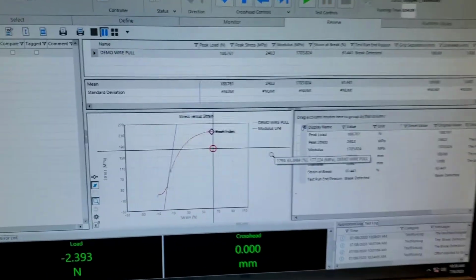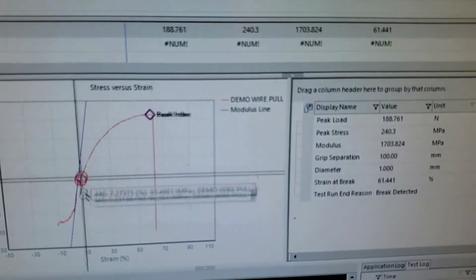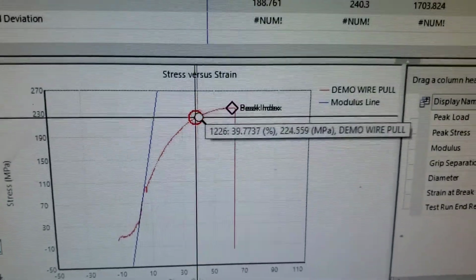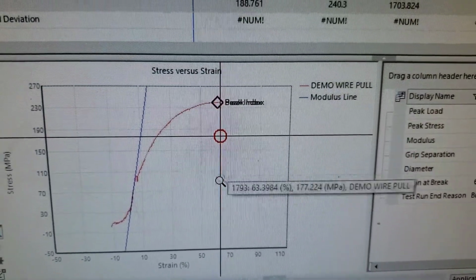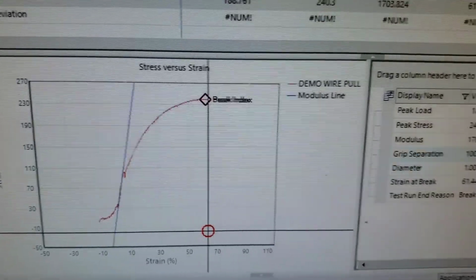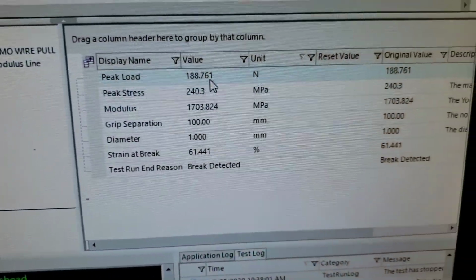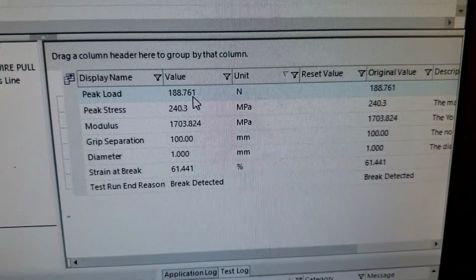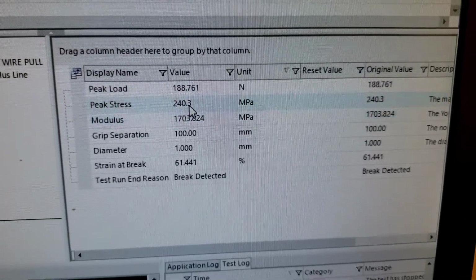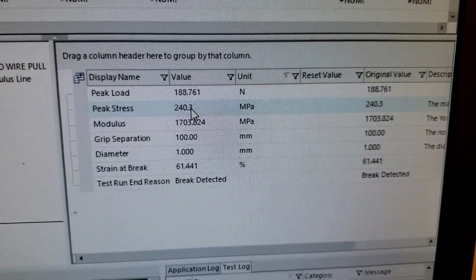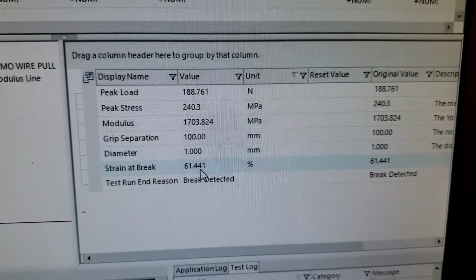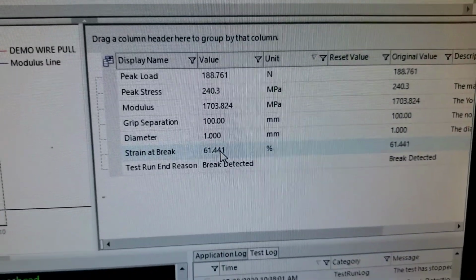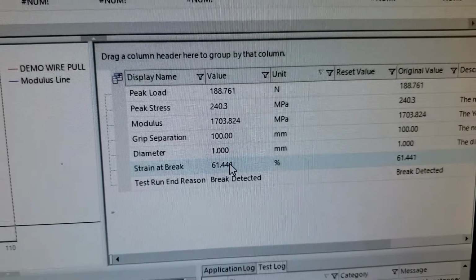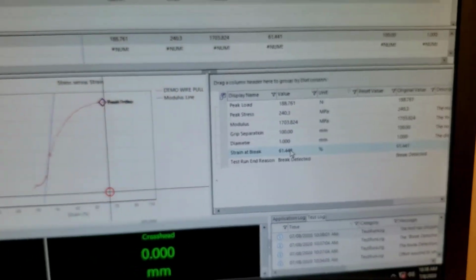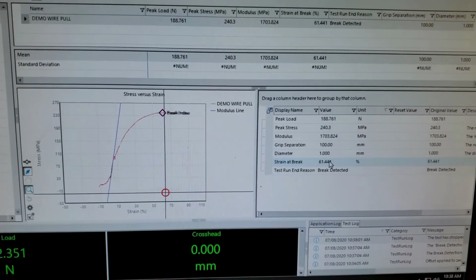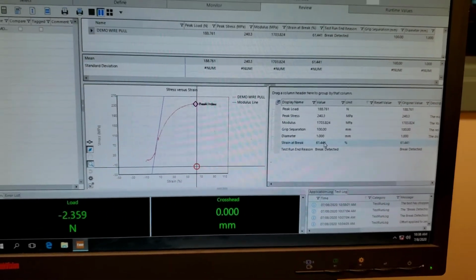And there it is. And notice again, we get this beautiful sawtooth curve indicating our break point here, and we can see that the peak load was just under 189 newtons, and that equals a stress of 240 megapascals, and the strain at break was 61.441%. So this copper wire extended itself 61% over its original 4-inch length. Rather amazing.